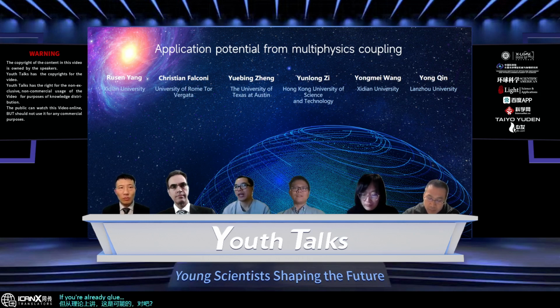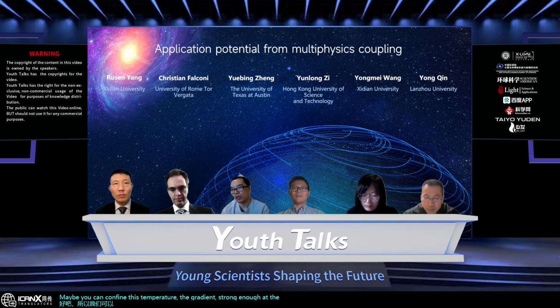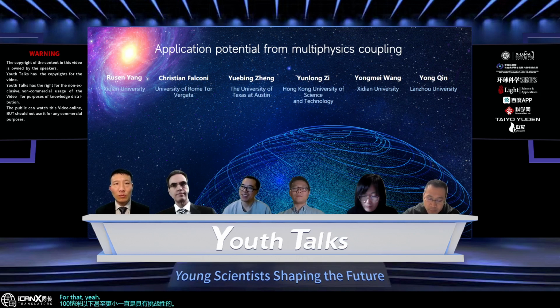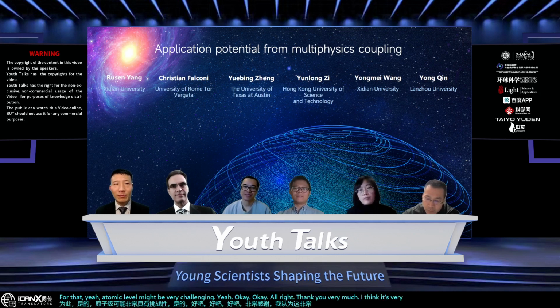Theoretically, we can use a single nanoparticle as a heating source. So we can maybe confine the temperature gradient strongly enough at below 100 nanometer, but going smaller has been challenging. At the atomic level might be very challenging. Okay, all right. Thank you very much. I think it's very interesting. Thank you.